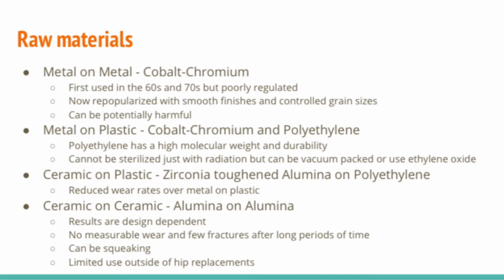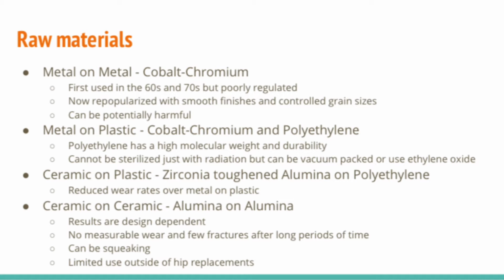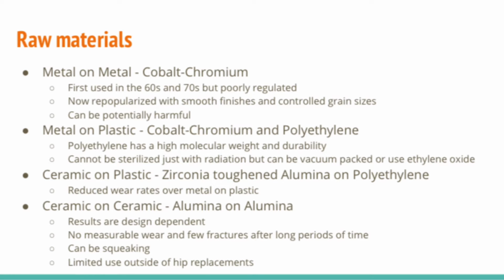For ceramic on ceramic joints, the results are design dependent. Some reports for this material show no measurable wear and very few fractures. Some people have reported squeaking when in motion, but no other important side effects. Ceramics have a very limited use outside of hip replacements due to non-conforming surface shapes of other joints. It makes the parts very difficult to manufacture and control the quality of.